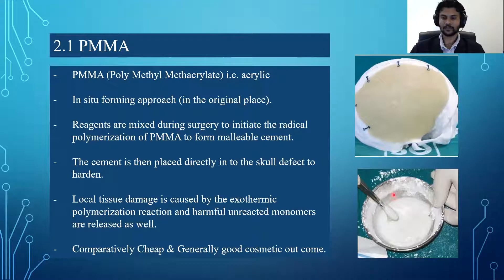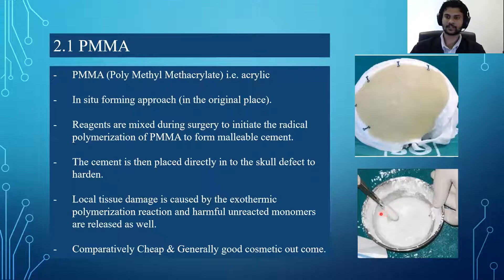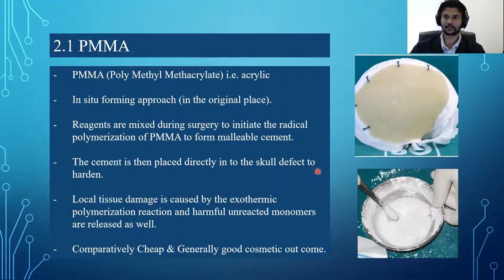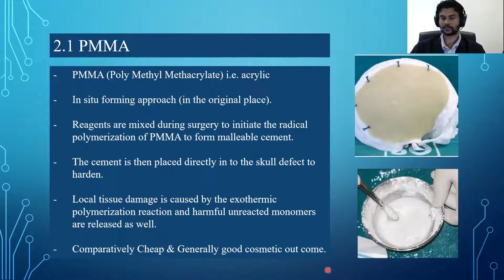However, that polymerization reaction is exothermic, meaning it releases a lot of heat, and that heat can cause burn damage to the local tissue area. What's more, not all the monomers react during polymerization, and these unreacted monomers are harmful to the human body. But despite these downsides, PMMA is the most used material in cranioplasty because it is cheap and results in a good cosmetic outcome with a low complications rate — if done properly.